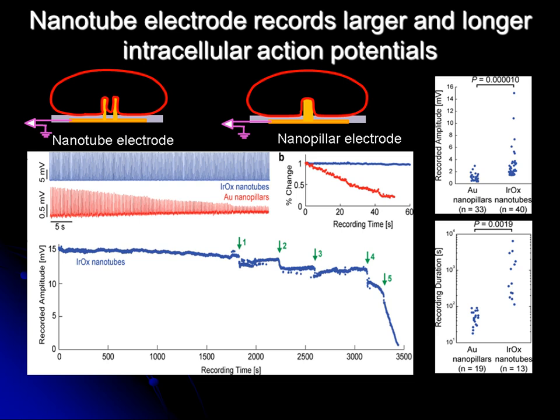So we compare the difference between nanotube electrode and nanopillar electrode. The blue traces are the nanotube electrode recording. The red traces are the nanopillar electrode recording. As I showed in the previous few slides, in nanopillar electrode recording, the cell membrane recedes pretty fast, in a few minutes. And therefore, we see the decay of the amplitude pretty quickly. On the other hand, for nanotube electrode recording, we often see very constant amplitude of the action potential for the first few minutes. For a few particular cases, we actually see intracellular recording for up to an hour. So nanotube electrode records about 10 times longer intracellular access than nanopillar electrode. It also recorded twice as large amplitude.